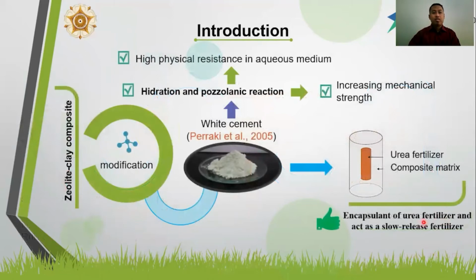To overcome this problem, we use white cement because white cement results in hydration and pozzolanic reactions. Both reactions produce a strong and compact composite and can rearrange the microstructure of the composite. As a result, the composite we made has a high physical resistance in aqueous medium and also a high mechanical strength. Therefore, a modification using white cement in zeolite clay composite is expected to act as an encapsulant of urea fertilizer and also act as a slow-release fertilizer.